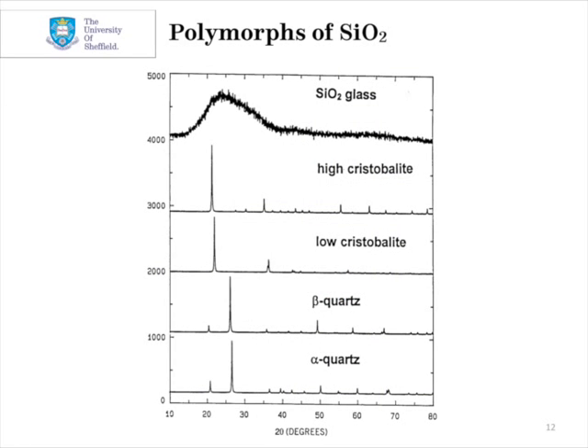Similarly, if we look at silica, we can see that the alpha and beta quartz polymorphs of silica have very similar diffraction patterns, just some subtle changes here and there in the smaller reflections. And this is because the crystal structures are very similar for these two.